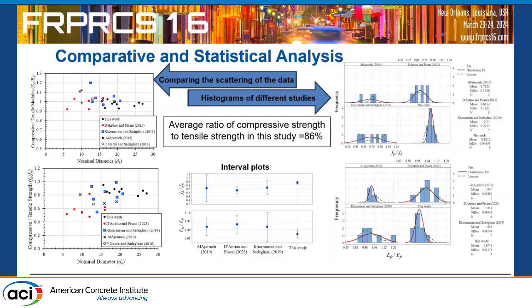Yeah, in tension you have the cracking of matrix, but in compression there is no cracking. So modulus sometimes could go a little bit higher. But one thing is that in terms of variation, we have the smallest variation and the most consistency. And here are some histograms showing the variation of what we have got in terms of modulus of elasticity and in terms of compressive strength. So overall, the average ratio of compressive strength to tensile strength in this study is 86%.